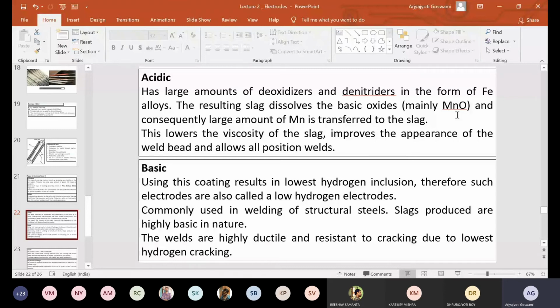In those cases, acidic fluxes are good, because they generate a kind of slag which readily combines with manganese oxide and takes out the manganese, right? This lowers the viscosity of the slag and improves the appearance of the weld bead and allows all position welding. So viscosity of the slag is also an important factor. If the viscosity is very high, then the weld appearance will not be good, the slag will flow everywhere, right? If the viscosity is low, then we cannot use it for overhead welding, because the molten slag will not be able to hold its position. So acidic fluxes can be used for all position welding.